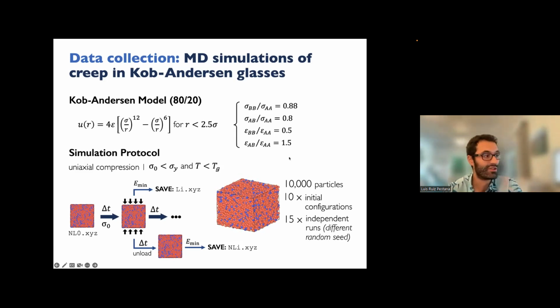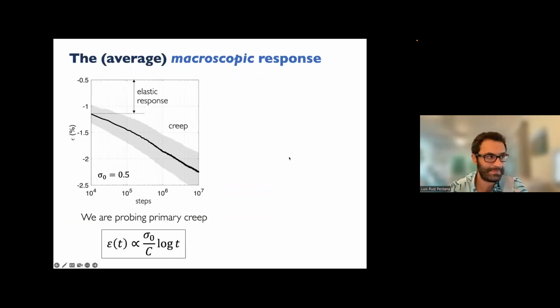Okay, so how does the macroscopic response look like? Well, it looks like this. So here what you are seeing is a strain versus time, the number of steps actually. All the units here are Lennard-Jones units. They are related to the Kob-Andersen glass, so they are not going to make a lot of sense compared to megapascals, gigapascals or things like that. So when I say that the stress is 0.5, the important part here is that the yield stress, for example, for the Kob-Andersen glass is 1.2. And the temperature that we simulate is very well under the glass transition temperature of the Kob-Andersen glass.